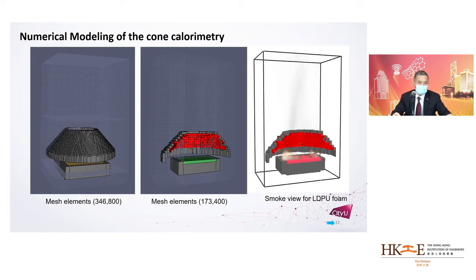Now, in this calculation, we use FDS, which is a well-known software developed by NIST for fire calculation. The only thing that we make use of from the previous discussion is the chemical kinetics, the pyrolysis kinetics that we obtain from the KAS analysis based on the TGA experimental result. So from the TGA, which is a bench scale experiment involving a very small sample,